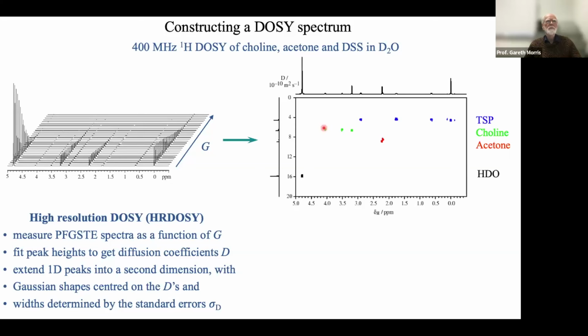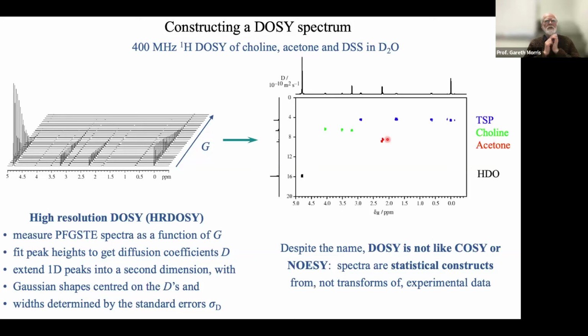Worse, because our D comes from fitting noisy data, not only does it have an uncertainty, sigma D, which we can represent with a width, but of course the center of the Gaussian is going to be in different positions depending on the noise. And so the fundamental point here is that DOSY isn't like COSY or NOESY. It may come out flat in two dimensions, but these spectra are statistical constructs. They're not the result of a double Fourier transformation of experimental data.